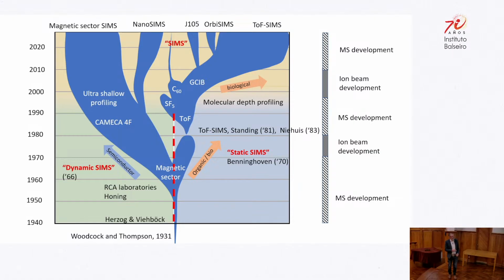But another branch formed off, led by Professor Alfred Benninghoven in the 70s. And this was really steered towards looking at biology and organics. But as I described, you get this Darwinian process, so the kind of mass spectrometers they used at the time were not really very good for this application. And then there was development of new mass spectrometers, so-called time-of-flight mass spectrometers, which could detect all the molecules in one go. But the downside of these time-of-flight mass spectrometers, as we'll see later, is they're not very accurate in terms of identifying what the molecule is, because their peaks are very broad and they're not very accurately located.